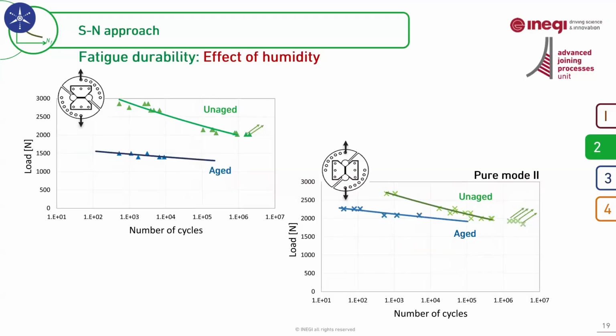Another parameter that we analyzed is the effect of moisture. We have performed similar tests under humid conditions. Again, moisture causes a substantial reduction in fatigue life in both loading modes, of course, but mode 1 is much more sensitive to moisture than mode 2. And that's one of the reasons, again, that designing joints in a way to be loaded in shear is recommended.